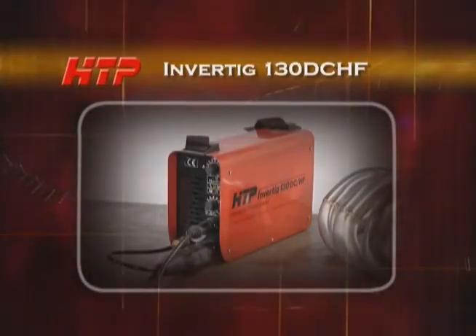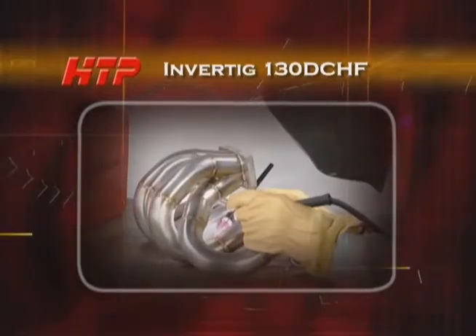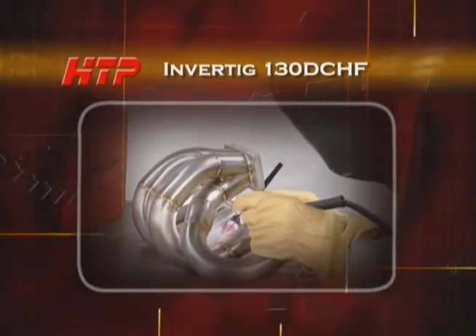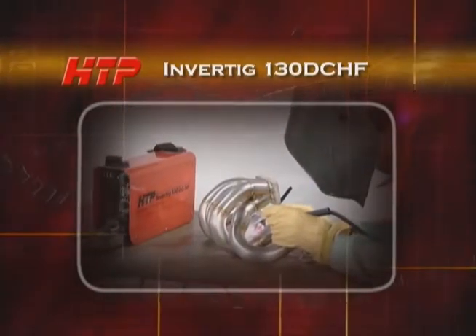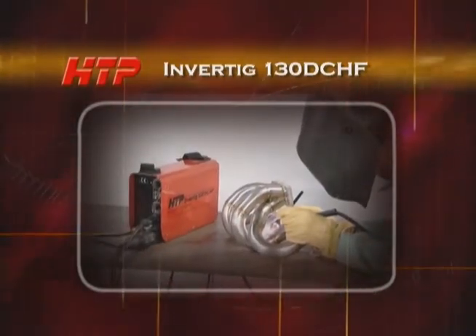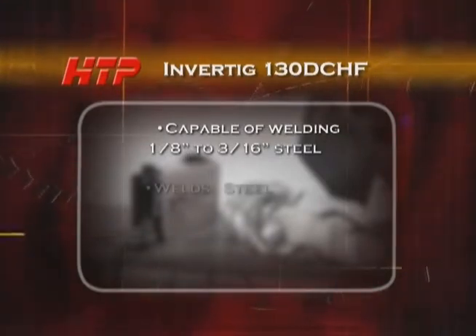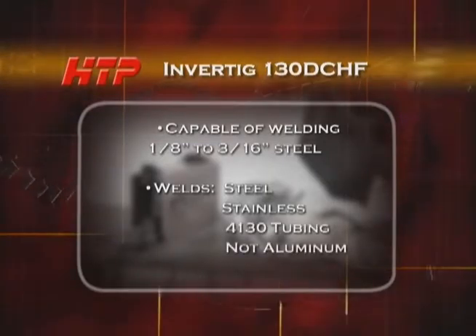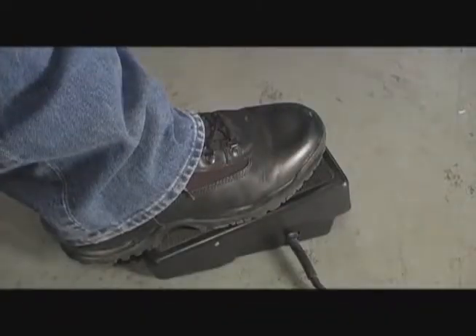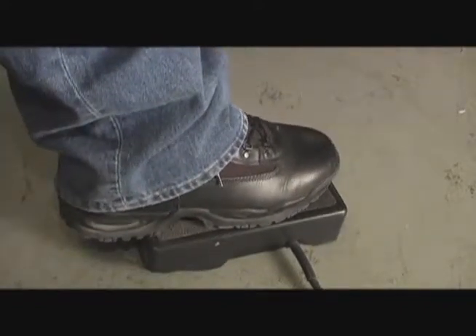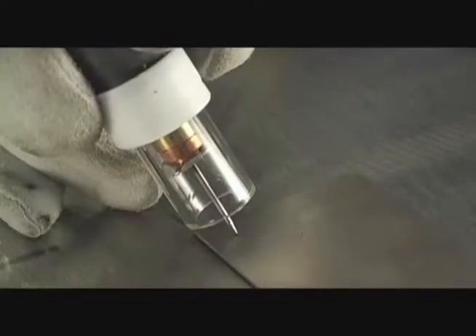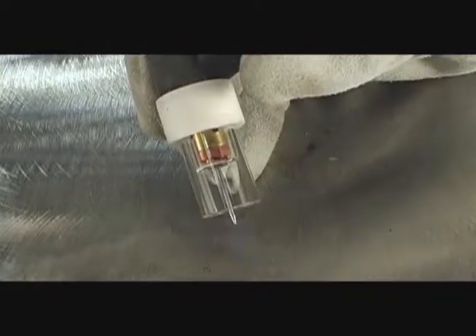The InverTIG 130 DCHF is a 130 amp DC TIG stick welder which operates on a 25 amp 220 volt single phase circuit. 130 amps of power means that the 130 DCHF is capable of welding 1/8 to 3/16 inch steel depending on the application. The 130 DCHF will weld steel, stainless, 4130 tubing, but not aluminum. The 130 DCHF also has a remote amperage control by foot pedal. The 130 DCHF starts the arc by either touch starting or high frequency.